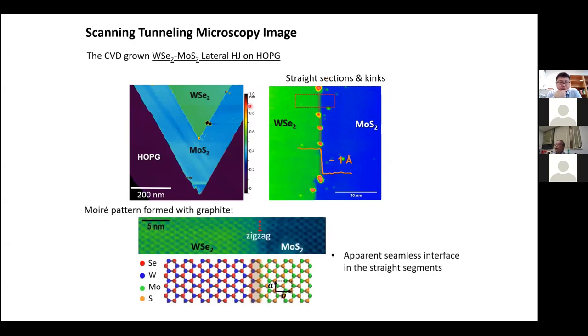Now let's zoom in and look at the structure, and you'll see this is not an atomic image. This is really the so-called moiré pattern between the TMD and the graphite. So the periodicity is about one nanometer. But the moiré pattern shows an almost perfect interface. That implies an almost perfect interface atomically, okay? And you say, well, okay, this is what is expected. This is a pseudomorphic strain over there.